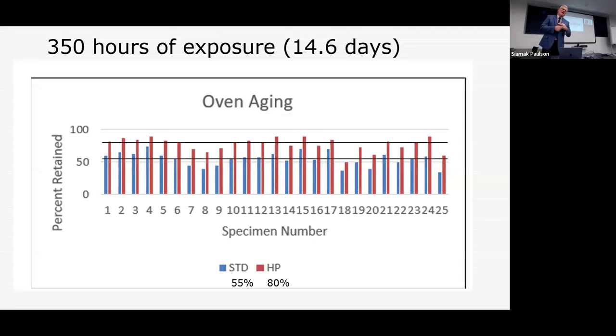That's what 25 samples look like. The thresholds are drawn here, and you'll see for standard, it's 55%, and for high pressure, 80% is the threshold. There's a couple of weak children in there: number 8, number 18, number 25. Keep those in mind because you're going to see them 2 more times. They are GM13 materials, so they were the ones that we would know would fail. But the system seems to be working. Some very good ones we know are in there, but that's all hidden.